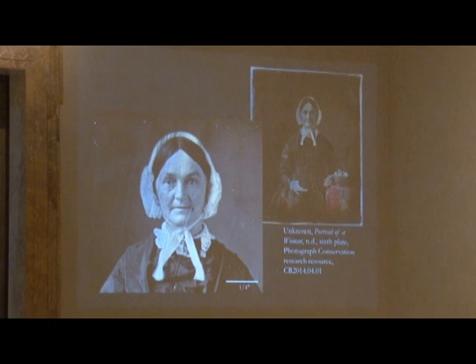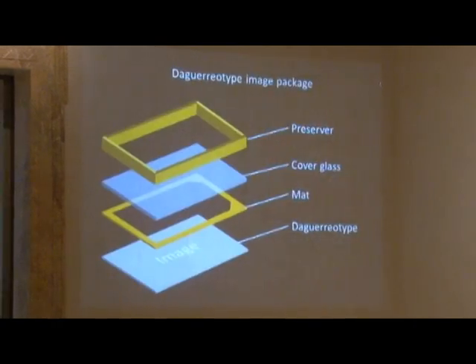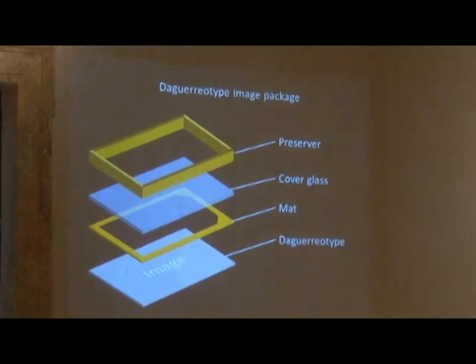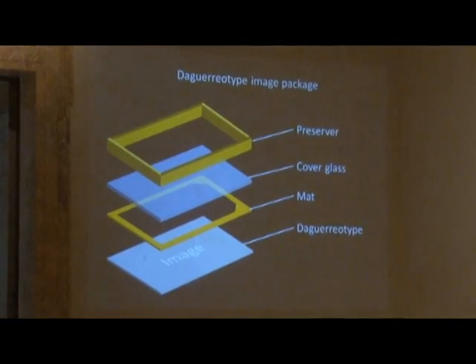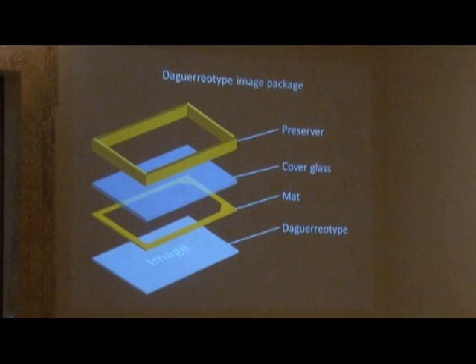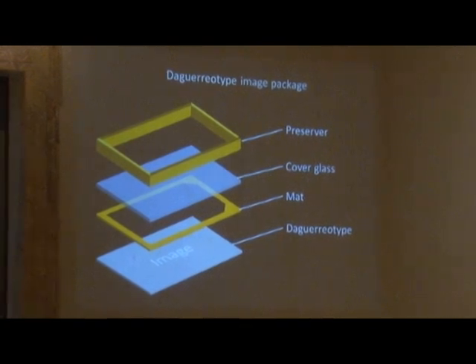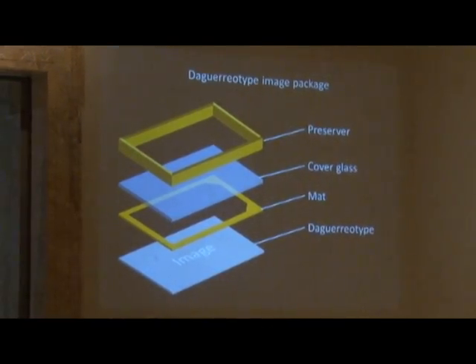Also, dust particles that sit on the daguerreotypes are really damaging as well. So to protect the fragile surface from these factors, they are covered with a piece of glass called cover glass. But even the smooth surface of the glass cannot come in direct contact with the image surface. So there's a piece of window mat placed in between, and that's usually made of brass or sometimes paper.